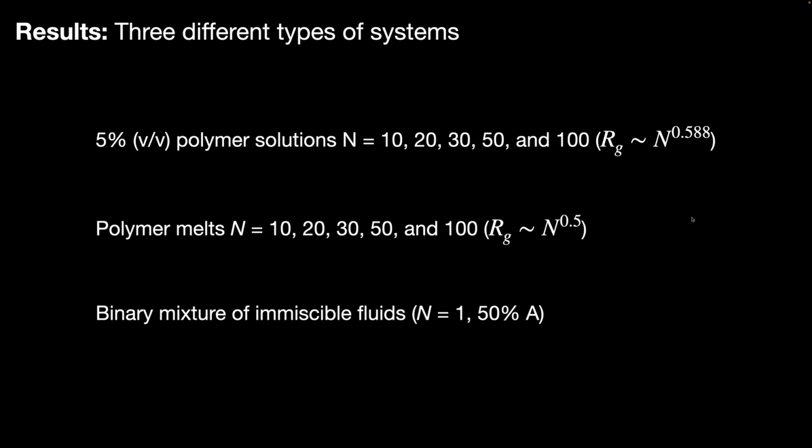Based on our knowledge of polymer physics, the radius of gyration should scale as the degree of polymerization to the 0.588 power in 3D. Actually, it's not the degree of polymerization here, it's the number of segments, the number of bonds. If the degree of polymerization is like 1,000,000, then the difference between n and n-1 is negligible. However, for our simulations, because our chain lengths are a maximum of 100, I subtracted 1 from the degree of polymerization to look at the scaling relationship, and we'll see what came out.